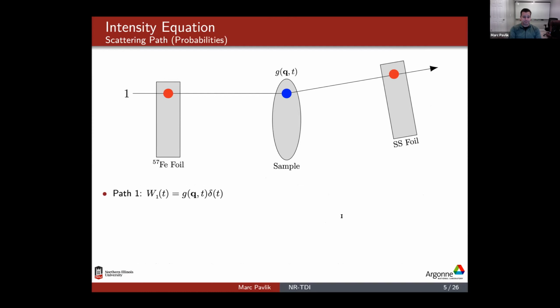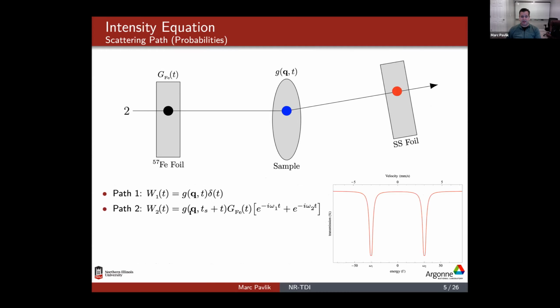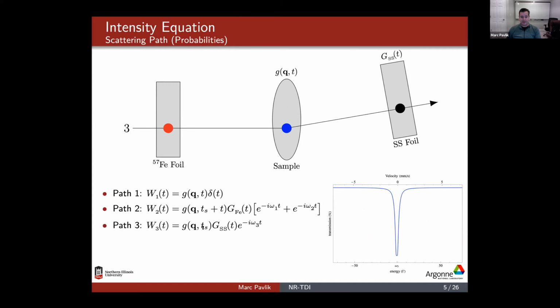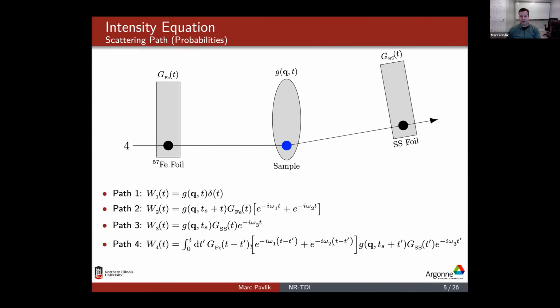Each path has its own probability. So the probability of path 1 is just the response function from the sample and the delta function from the prompt. The second path is a resonant response function from our foil, and because it's magnetized, we have a 2-line beat spectrum here, each indicated by omega 1, omega 2, and the scattering response function from the sample. The third path is again the scattering from the sample and the resonant function from our stainless steel foil. And the fourth path is the product of the response functions from the foil, sample, and stainless steel.